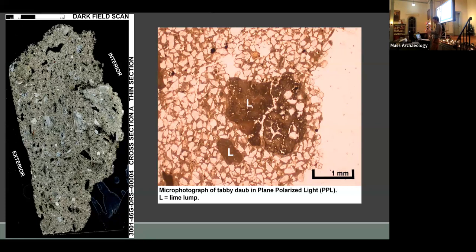However, from the historical record, it seems there was not a hard and fast rule to tabby making, and that really depended on the feel of the workforce and how they felt about the quality of the lime. They would adjust the ratio of the materials accordingly. And so once the materials were mixed, there's proportions. The workers had a few hours to apply the mix before it began to stiffen and lose its plasticity.